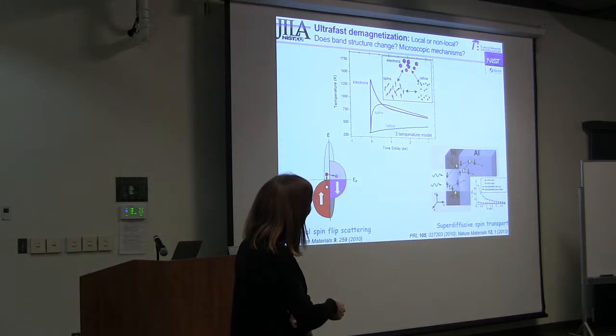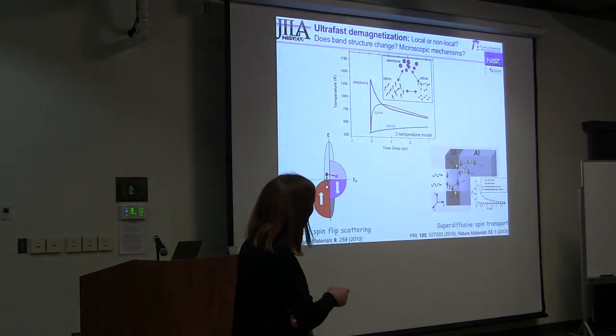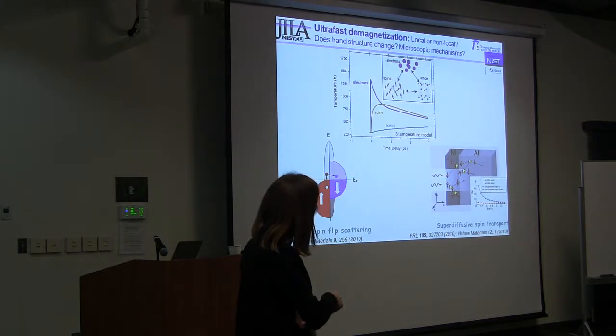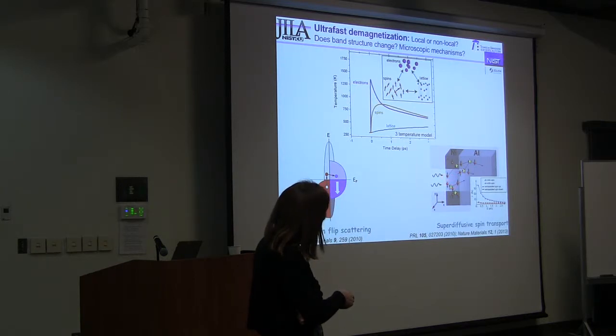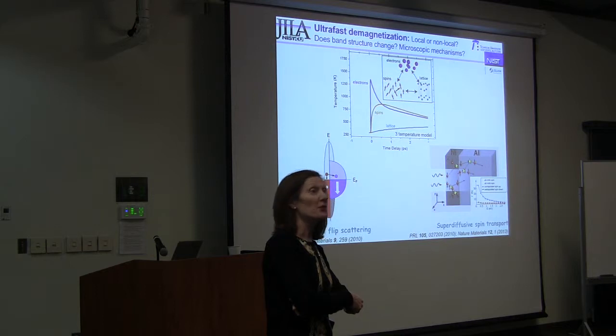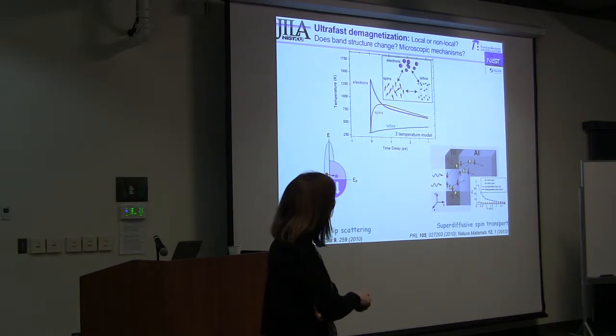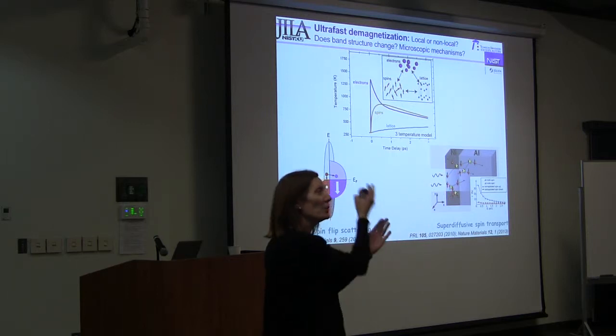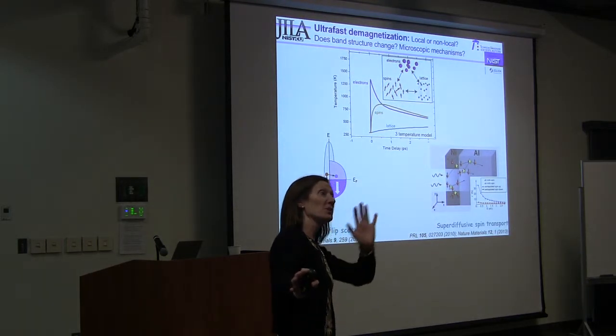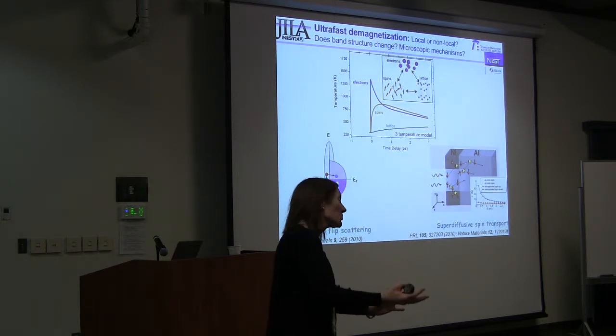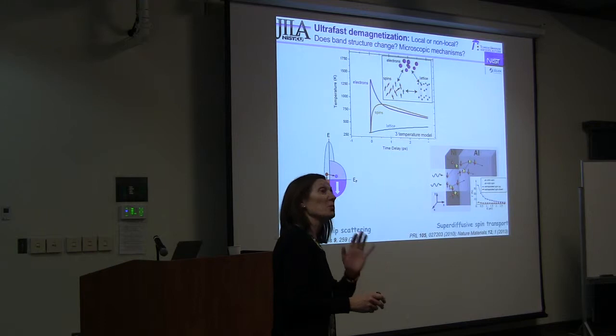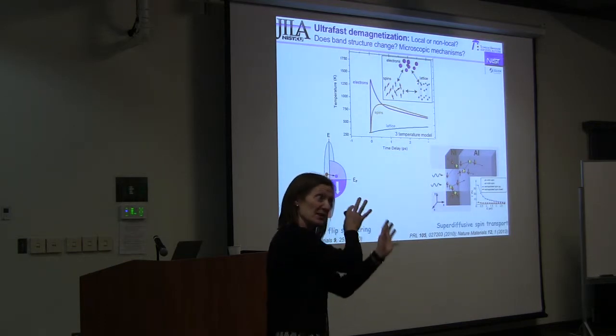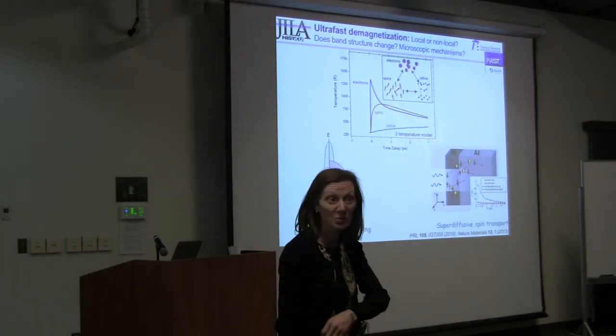Then a few years afterwards, Peter Oppeneer said that's not what's happening at all. It's not this local spin flip scattering. What happens is you've got majority and minority spins in the material, but their scattering lengths are not the same, and that's known. The spin ups can travel a lot further before they scatter, whereas the spin downs scatter almost immediately. So now you have this spin polarized current that goes out of the region you're probing, but there's always a return cold current, and that's not spin polarized. So it would look like the material demagnetized, whereas what happened is that a whole lot of spin polarized electrons rushed out of the probed region.